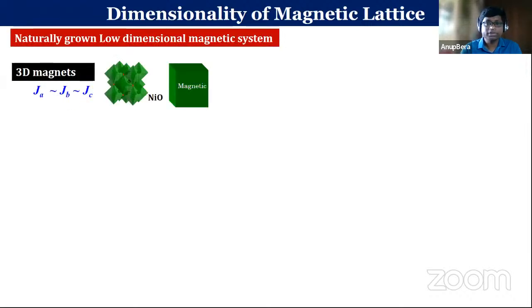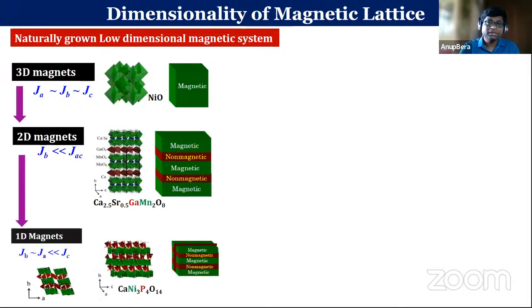And this morning, Professor Yusuf gave a nice introduction about low-dimensional spin systems, and that makes my job easy. So based on these 3-dimensional crystals, one can have different dimensionality. For example, if I take nickel oxide, where the magnetic ion is nickel, how the nickel ions are arranged in the magnetic lattice gives the interaction between the magnetic nickel sites. And if we see, nickel oxide is uniform all over the 3 dimensions, and it is a 3-dimensional magnet.